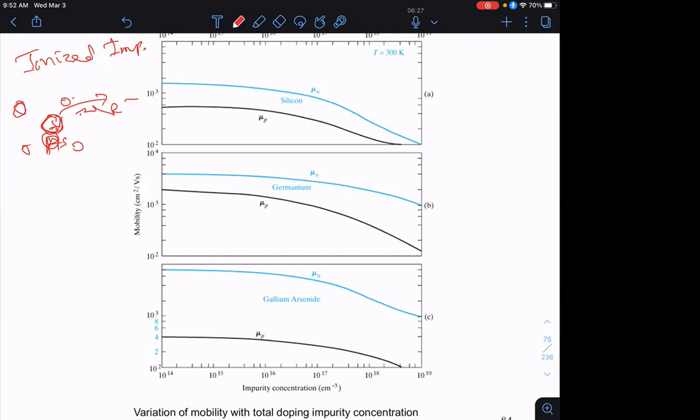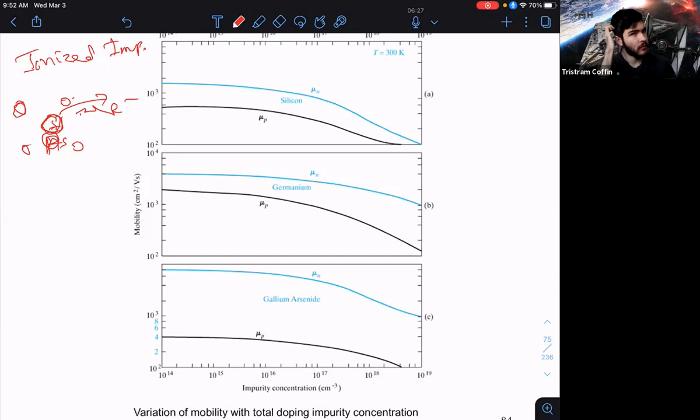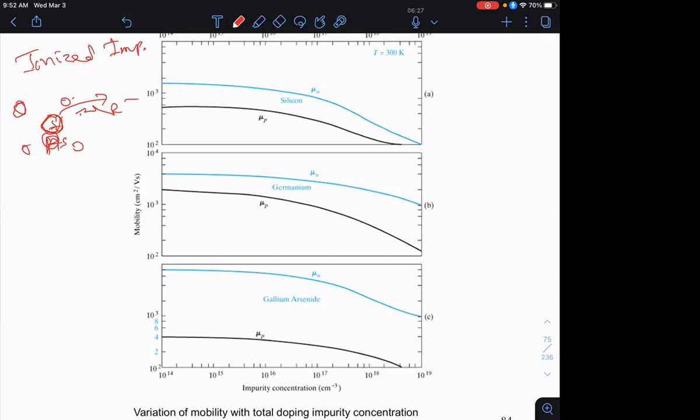So if I replace a silicon atom with a foreign impurity, an arsenic donor impurity, that's a different type of atom. It's different from silicon, right? Therefore, it's a defect. It's an intentional defect that I've created because I need to introduce electrons in my transistor, right? But it's a defect nevertheless. The arsenic is a defect. So as far as the electron is concerned, when it's moving in the vicinity of the donor impurity, suppose the electron was traveling like this, the electron is negatively charged, it'll be attracted by this positive donor impurity, right? And it may deflect like this.